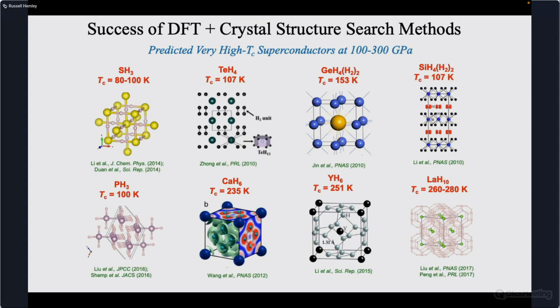So these techniques were used to great success in the early 2010-2012 period, and a series of different structures were predicted. This includes structures of sulfur and hydrogen, tellurium, silicon, germanium, phosphorus and hydrogen, and others, including these lanthanides. The LaH10 I'll mention because that was work that we did ourselves. And what emerged was that a lot of these were quickly confirmed experimentally, the first being SH3 or H3S, followed by our confirmation of our prediction of LaH10.